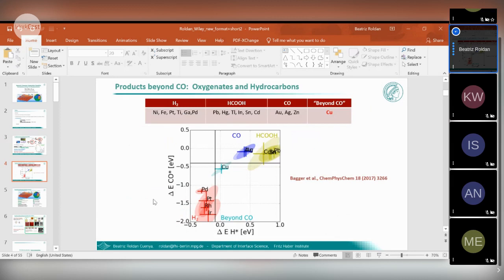So this is just an example from theoretical predictions, looking at what is needed. Why is copper so special? Why is copper the only metal that is able to produce hydrocarbons and alcohols? If you look at the literature, there are some metals that make hydrogen, some metals that make formate, others make CO, but it's actually only copper that makes significant amounts of hydrocarbons and alcohols. This is attributed to the fact that copper has an optimum binding of adsorbed hydrogen and adsorbed CO. So in my talk, we are going to try to make copper even better and see what happens when I modify the structure and the composition of elements around copper.